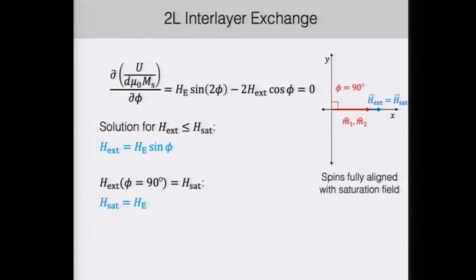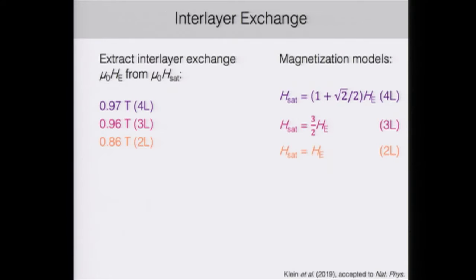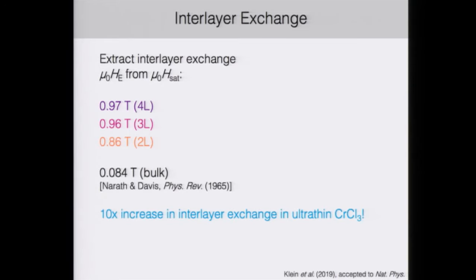And then in the case where we've reached saturation, we just set phi to equal 90 degrees for both of these layers. And then we find that in bilayer, the saturation and exchange should be the same. And then in trilayer and 4-layer, there's just a numerical prefactor. So now we can just write down these models and then extract the interlayer exchange value from the saturation. And what we find is that the interlayer exchange is about the same for our 3 different device thicknesses, but more importantly is a factor of 10 greater than the interlayer exchange in the bulk. So for some reason, we're seeing a 10-fold increase in this interlayer exchange in ultra-thin chrome chloride.